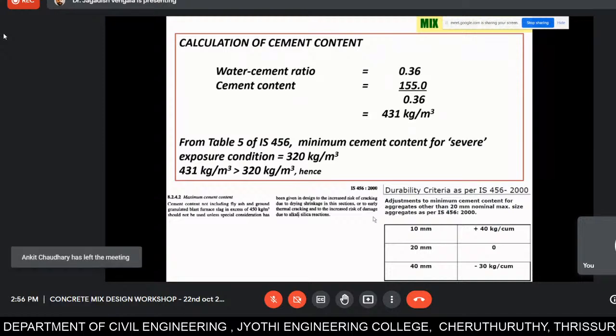But as per durability criteria, you have to do adjustments for minimum cement content. What does that mean? Suppose you are taking 10 mm coarse aggregates, so in place of 20 mm you are going for 10 mm down, you have to additionally add 40 kg per cubic meter. What does that mean? Your minimum cement content requirement is not 320, it is 360 kg per cubic meter if you are using maximum size of aggregate as 10 mm. Okay, I just wanted to give you a hint here.